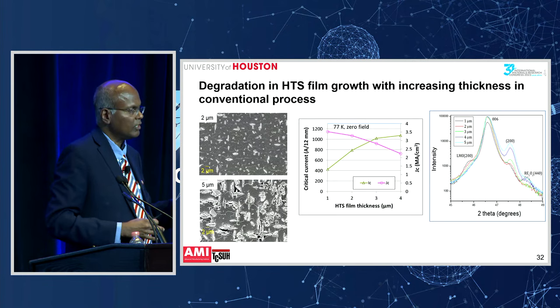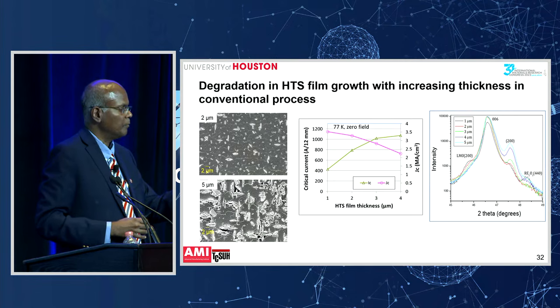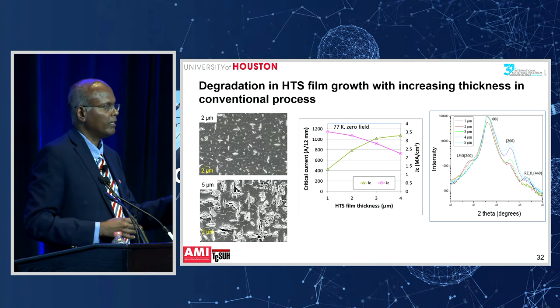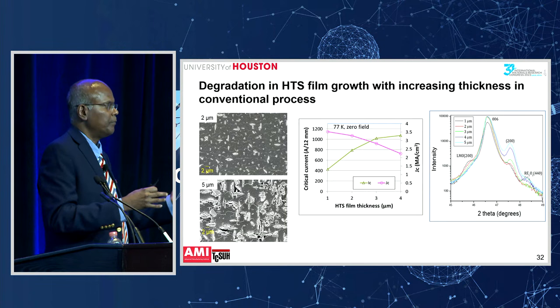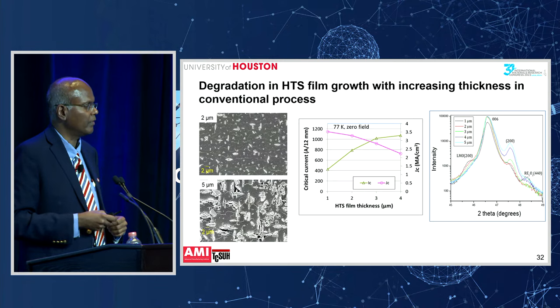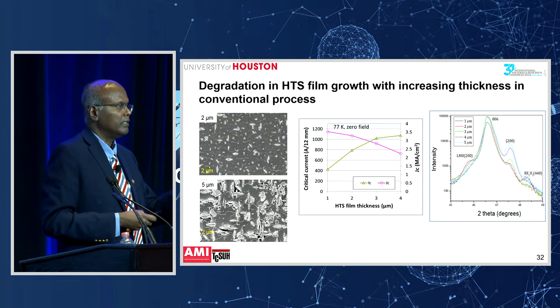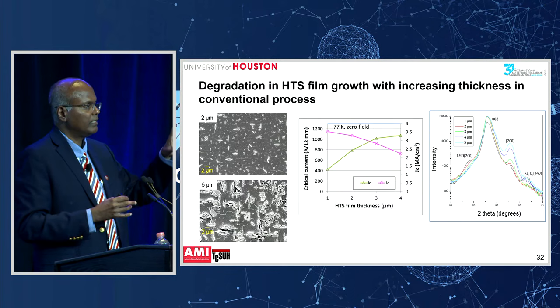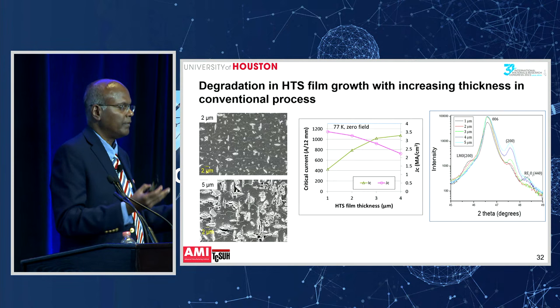And the reason for that, you can see both in the microstructure and from the X-ray diffraction pattern. On the microstructure, you can see when you go from 2 to 5 microns, you get a lot of misaligned grains. The epitaxy starts to break down. Right, if the epitaxial quality is not good, then it's not going to carry much current. You can also see in the X-ray diffraction scan, there's a 200 peak, right? The 200 peak is misaligned grains. The misaligned grain intensity keeps increasing as the film gets thicker. So initially we tried to optimize the process, but we could not. But then we realized it's not the process itself, it's the equipment that needs to be improved.